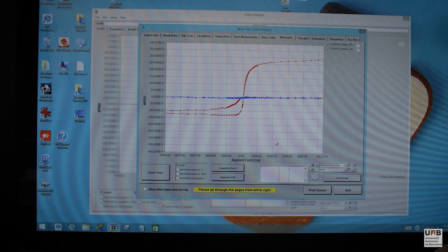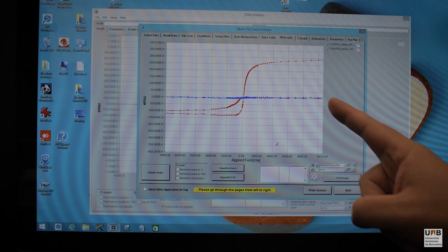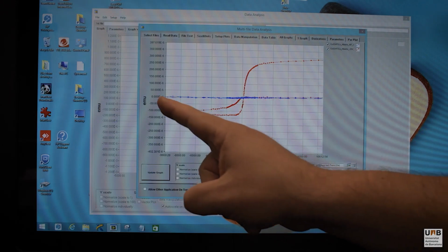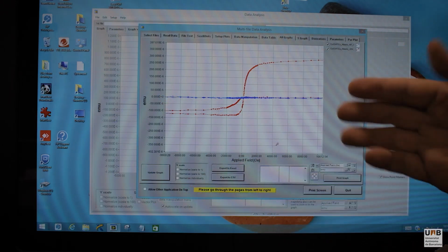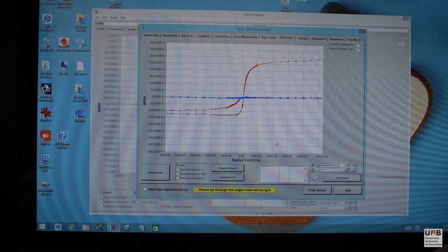Here is what our sample looks like after it's been treated with voltage. The blue line I've left in as reference what it originally looked like. And the red one is the loop as measured during the voltage application process that you saw me set up. This loop takes about 25 minutes to complete, and you'll see the hysteresis loop shows an increase in magnetization over time up until it reaches over 200, nearly 300 micro-EMU, showing a clear appearance of a magnetic signal, evidencing that we removed oxygen from the sample.